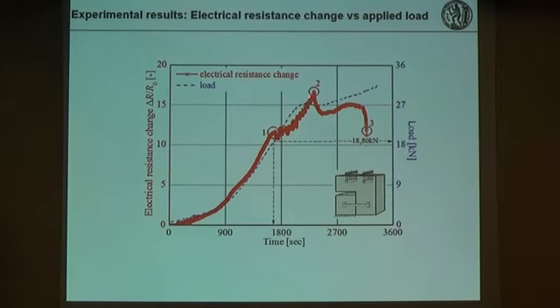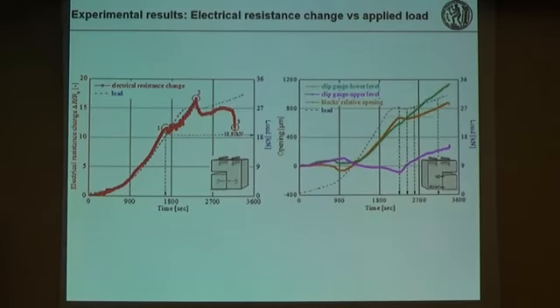After point 2, there is a decrease and then a small increase of the electrical resistance. In order to explain that, we can look at the results of the clip gauges which were attached at the rear side of the specimen. The orange line is the block's relative opening displacement curve. If we exclude the first part, the similarity of this curve with the load time curve is astonishing.